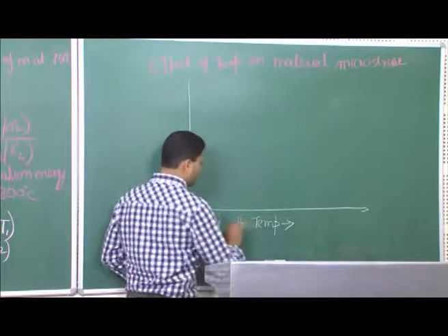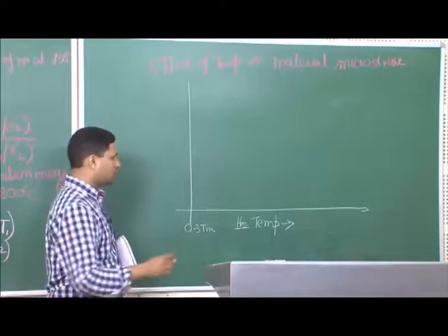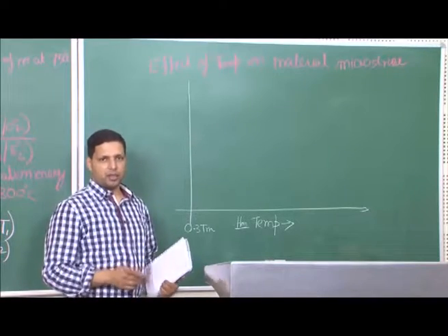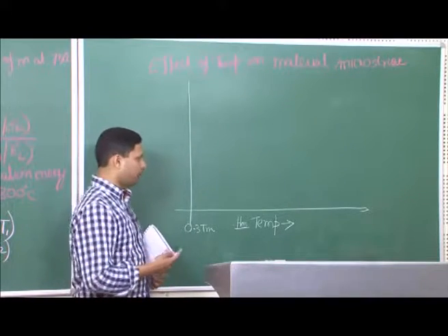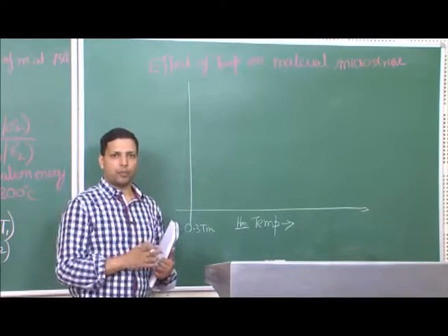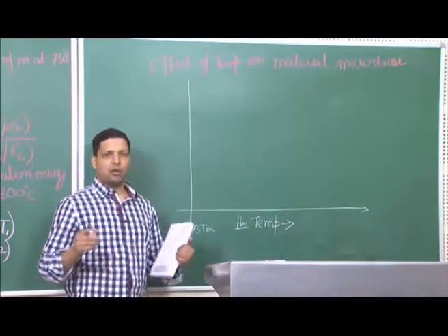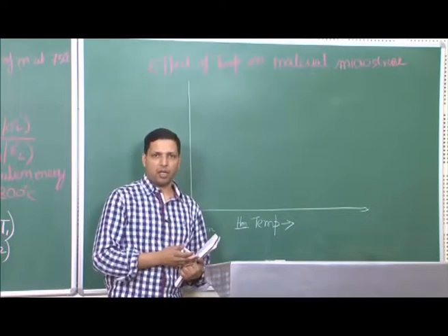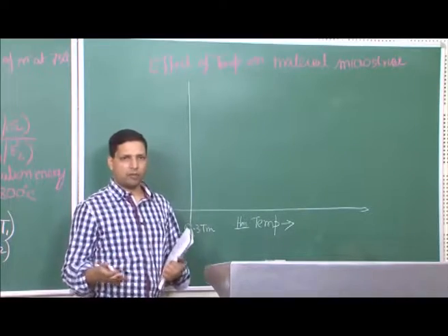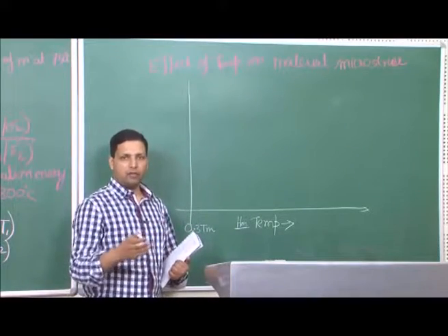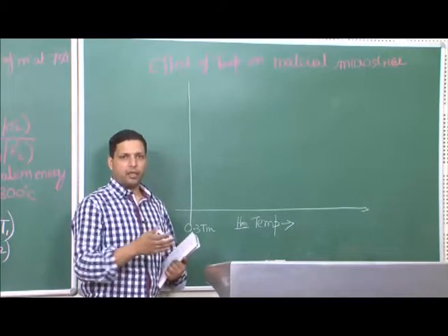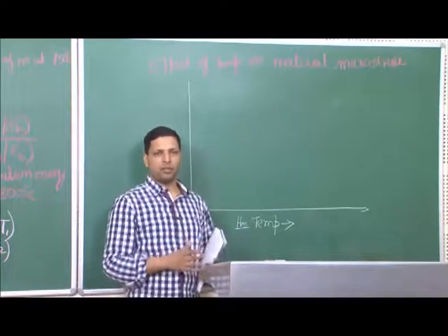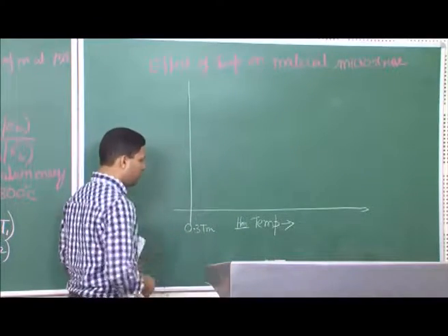Again I am using homologous temperature. Remember, homologous temperature has a lot of utility, because using it the behavior of several materials can be shown in a group. For example, aluminum may have a melting point of 660 while copper may have 1100. So, their behavior will be different when we are looking at 300 for both of them, but when we look at 0.3 Tm their behavior will be similar, and therefore, it is easier to group them together.